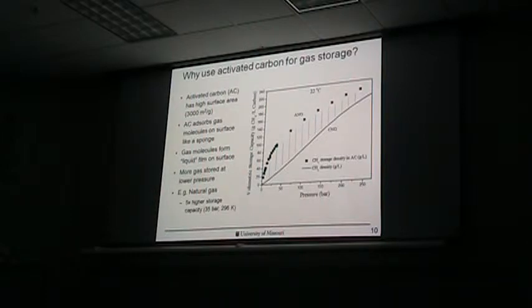And to give you an example for this, if you look at this black line here, this is how much you can store if you just compress the natural gas. And this is the pressure at room temperature. And these black squares, this is if you adsorb the gas in activated carbon. So these blue lines show the difference between the compressed one and the adsorbed one. You can see if you look at around 35 bar, you can store around 5 times more gas in your system compared to if you just compress this stuff.